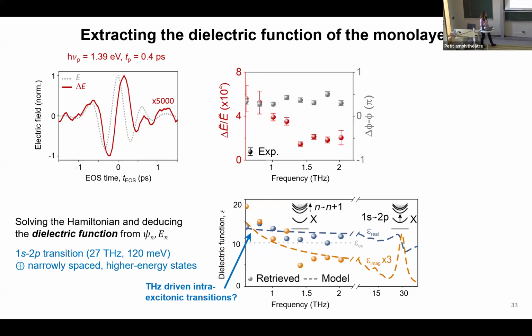And we were just curious to see whether by our model we can get an estimation of what the 1s2p transition could be in the case of a monolayer. And we estimated that the 1s2p transition should be at least 2 times larger in energy with respect to what we observed in the case of the bulk.